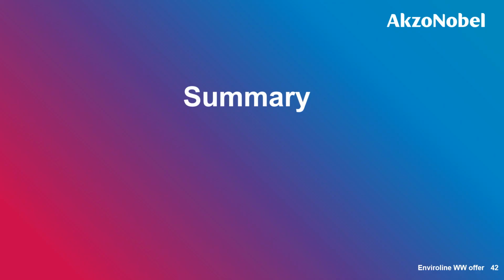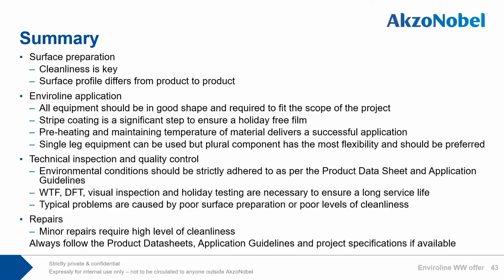And to summarize all that you've listened to and read in the past 40 minutes, and to wrap it up, for surface preparation, cleanliness is key and surface profile does differ from product to product. For application, all equipment should be in good shape and required to fit the scope of the project. Stripe coating is a significant step to ensure a holiday-free film. Preheating and maintaining temperature of material delivers a successful application. Single leg equipment can be used, but plural component has the most flexibility and should be preferred.